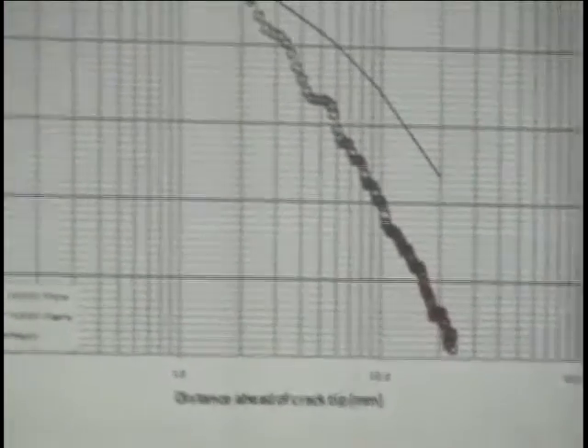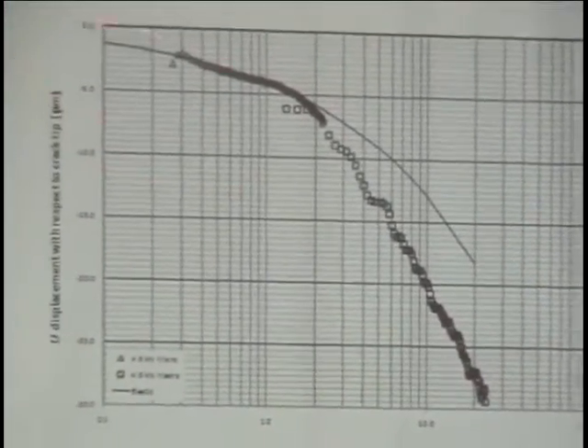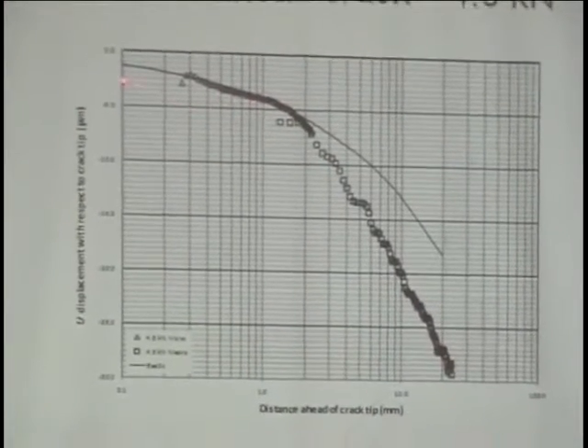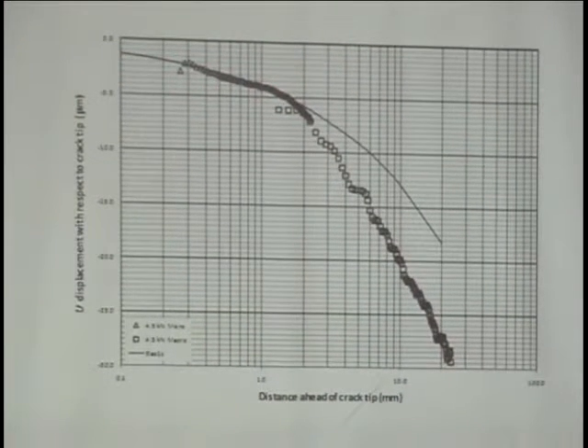you see further away from the crack tip, but this is just along the horizontal line. The data falls away. But what's interesting about this data for both is that even though it's on 2 different sides, we get very good continuity between the micro and macro displacement fields. So you sort of just get this continuation quite even about 15 millimeters, about 20 millimeters behind the crack tip.